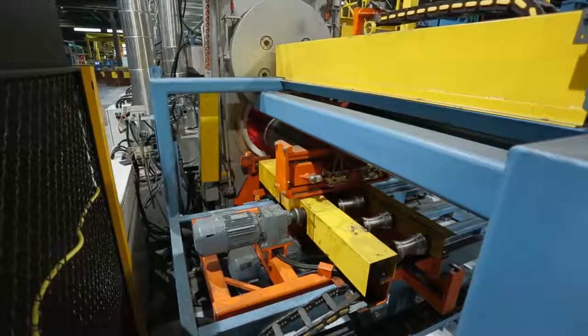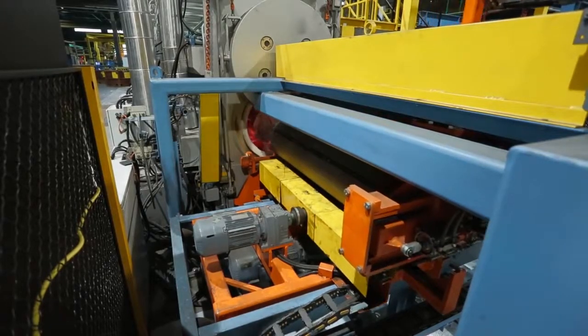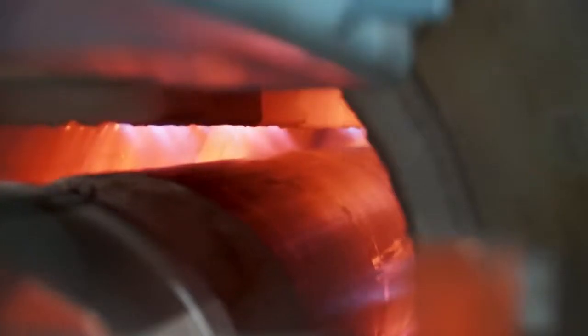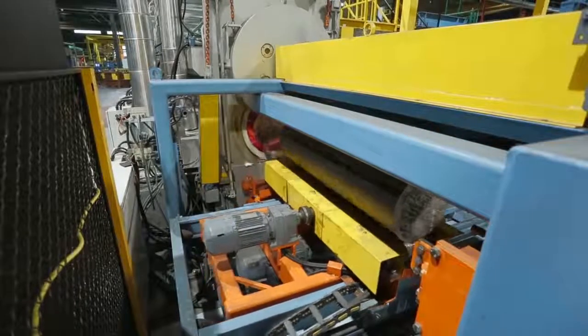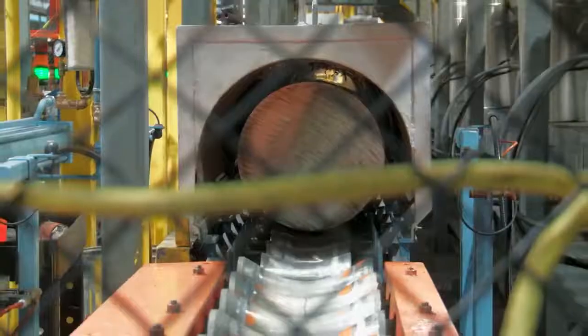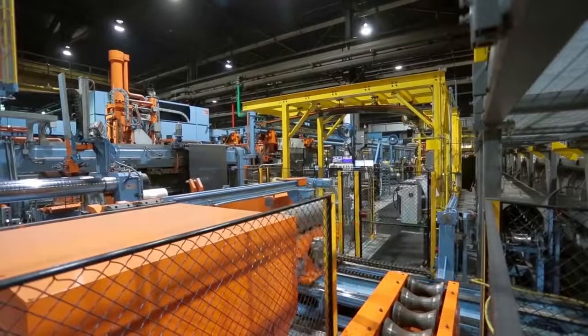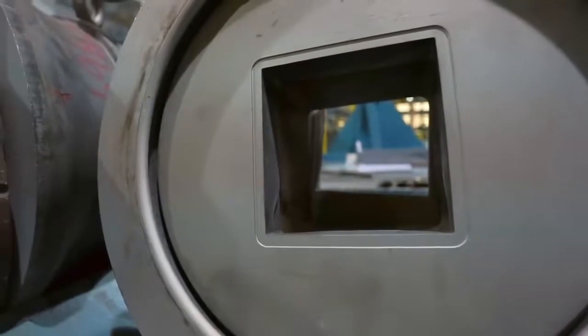Prior to extruding, we reheat the billets to a temperature that makes the material malleable, and in the case of 6000 series alloys, to achieve the desired strength requirements. Depending on alloy temper requirements, the temperature may be 800 to 1000 degrees Fahrenheit. It is critical that the billet is heated uniformly throughout using gas-fired furnaces or induction heating. Besides the billets, we also need to heat the dies to a suitable temperature. Extruding hot billets through a cold die is dangerous and can result in a broken die.